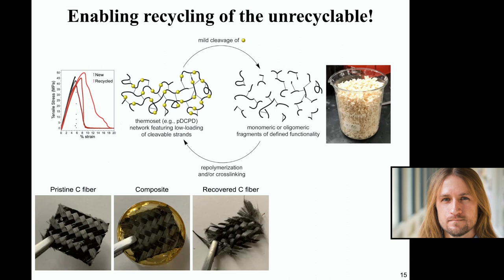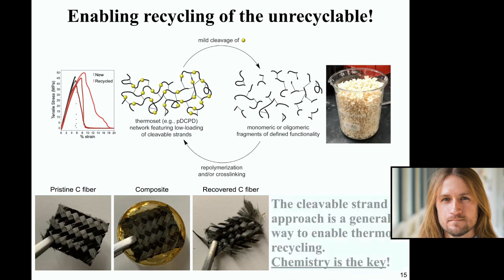Well, this is where our ability to very mildly dissolve these very strong polymers comes into play. So here, Peyton took a sample of pristine carbon fiber, embedded it into a sample of polydicyclopentadiene, forming a composite. And then by simple exposure to fluoride ions, he could dissolve away that plastic component, the pDCPD, and recover the carbon fiber. And we were able to show that the carbon fiber is completely untouched at a molecular scale. So our ability to dissolve the plastic didn't hurt it at all.